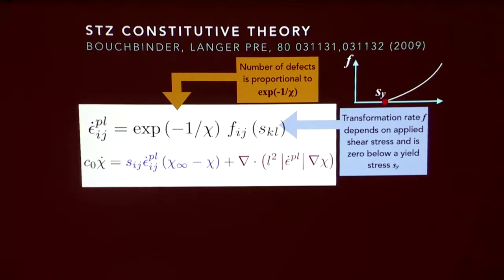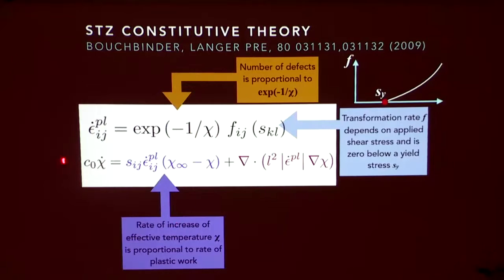And then I have to define also how the effective temperature is changing as I deform the system. So the rate of change of the effective temperature depends on the local rate of plastic work. If I'm doing work on the system, some amount of that work is going to raise the temperature. It's going into the structure to disorder the structure.